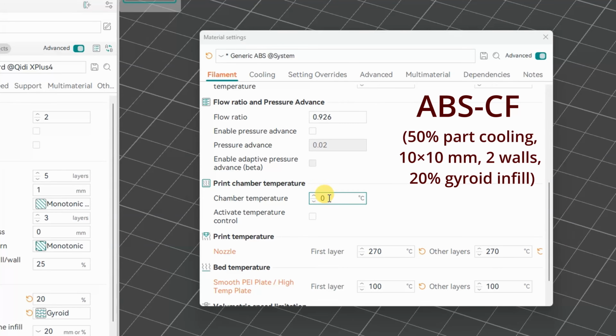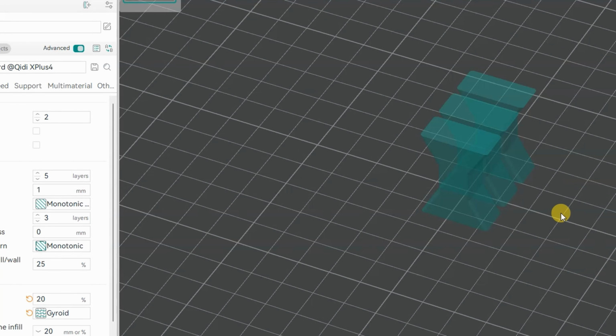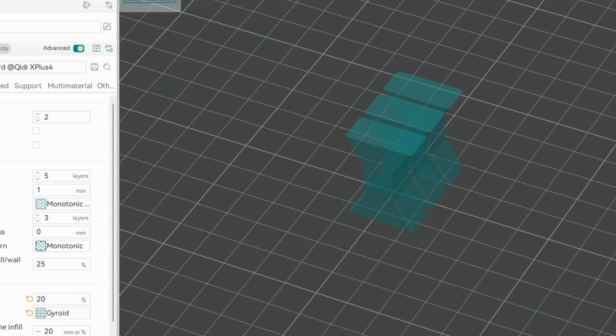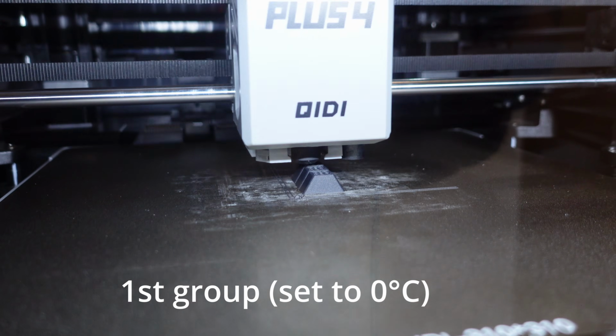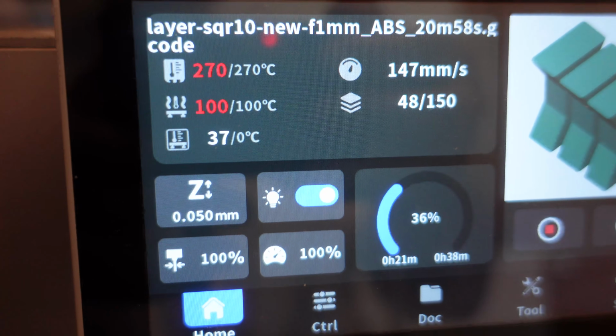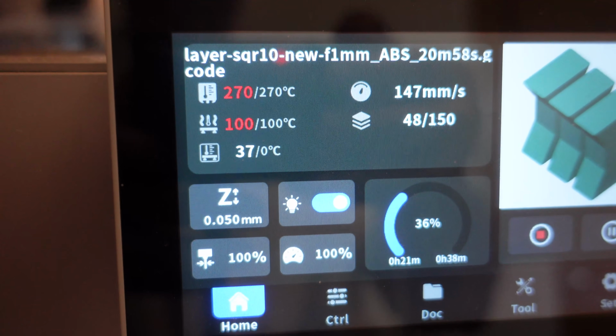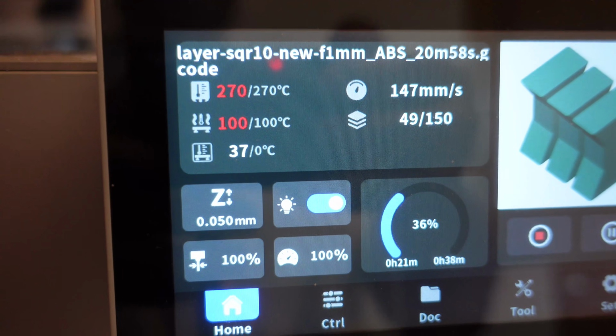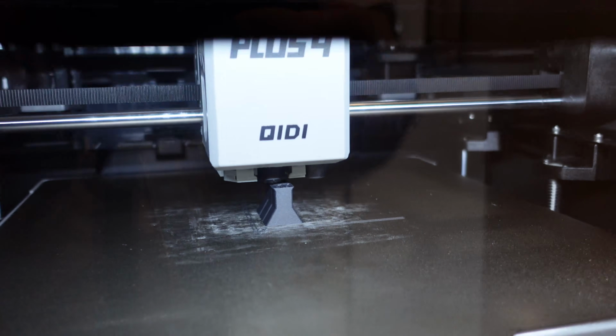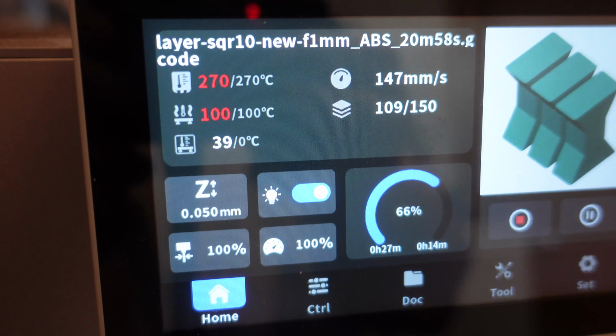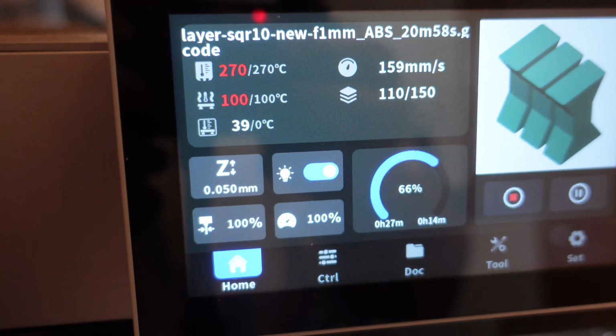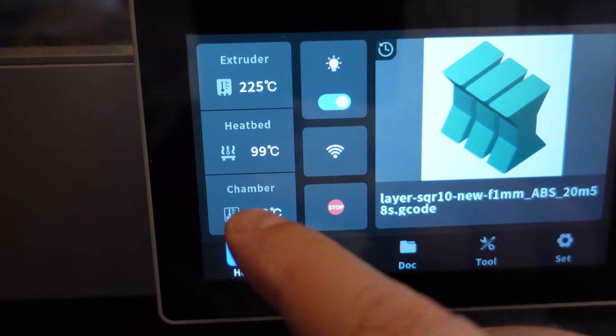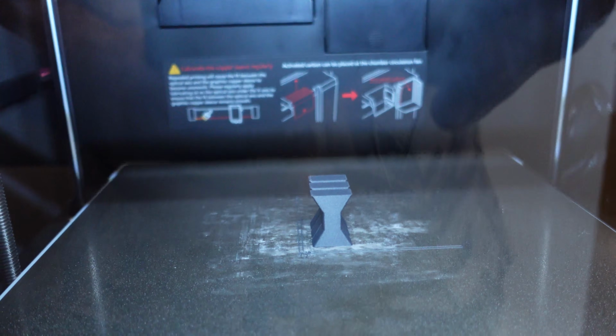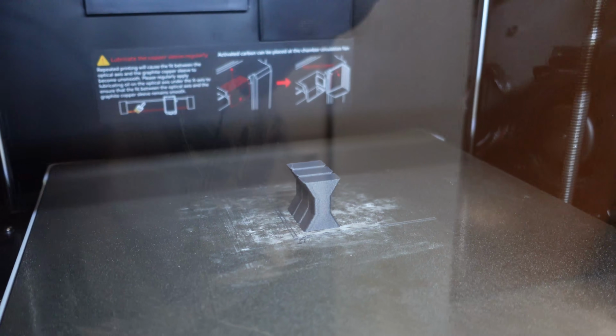Let's finally measure the effect of the actively heated chamber, so the only difference will be set temperature to 0 and 65, and I'm starting with 0 degrees. It started with the smallest cross-section area, and according to the sensor, the temperature inside is 37 degrees Celsius. Theoretically, this is the weakest point. The smallest cross-section area is finished, and the temperature inside is 39 degrees Celsius. It's finished and the peak temperature was 42 degrees Celsius on the chamber in approximately 32 minutes, and they look perfect.